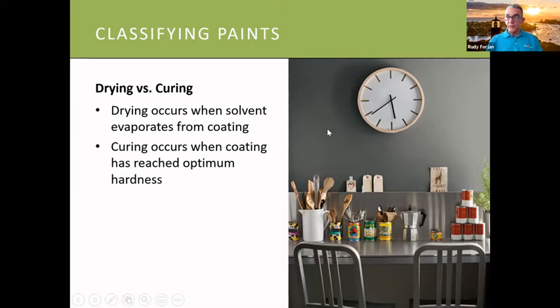Oil-based paints generally dry in about 4 to 8 hours. They cure generally within 10 days. In a perfect setting, latex paints generally dry in under 4 hours, and anywhere from 30 minutes to an hour at the most in our environment. And latex paints actually take a little bit longer to cure because of that process of coalescence that takes a little bit longer. So that could take up to 30 days.